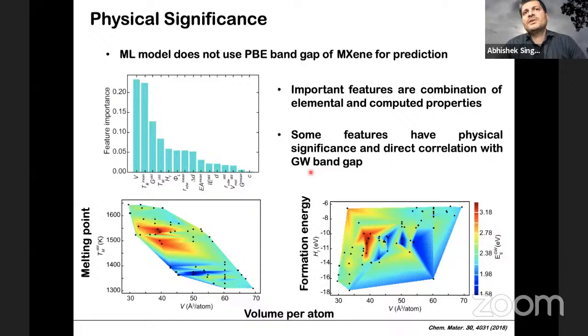This is what we would expect because the bond lengths are longer and therefore the wavefunction overlaps are smaller, lower, and therefore the splitting is lower, and eventually you'll get a smaller band gap, and vice versa if you have a smaller volume. And this is very nicely captured by our machine learning models also. So, again, causality is not expected, but we do see some of this already, and machine learning is able to capture those very nicely.